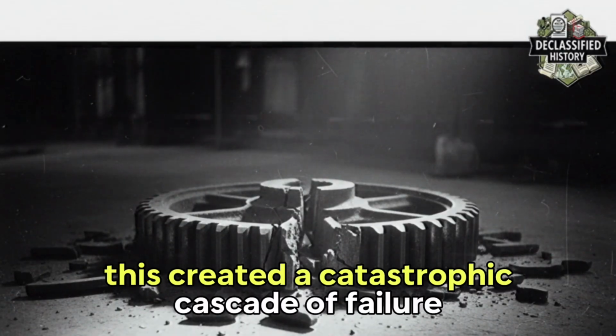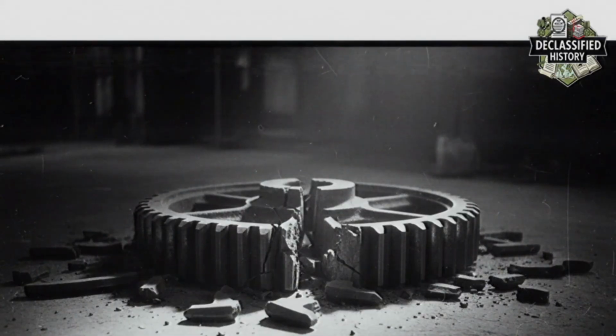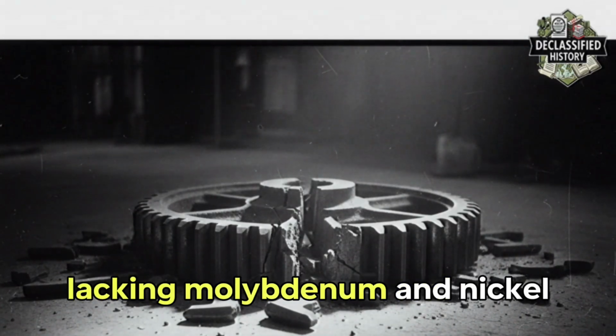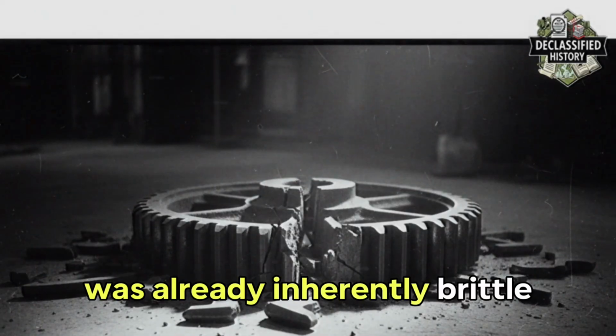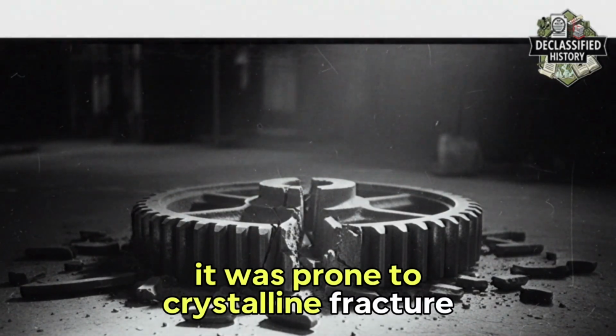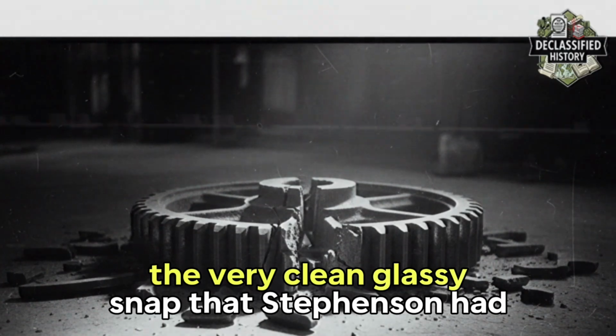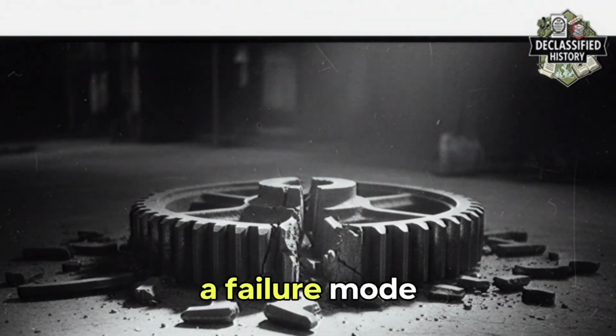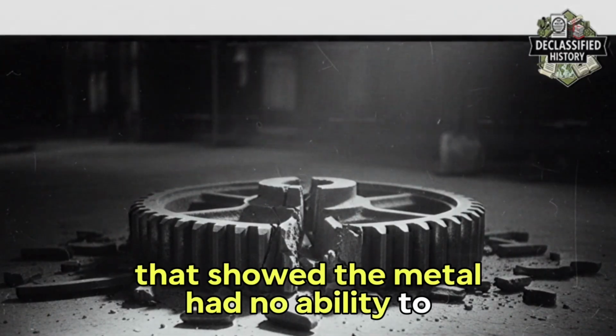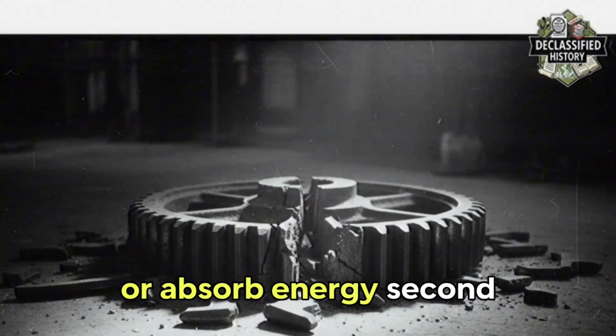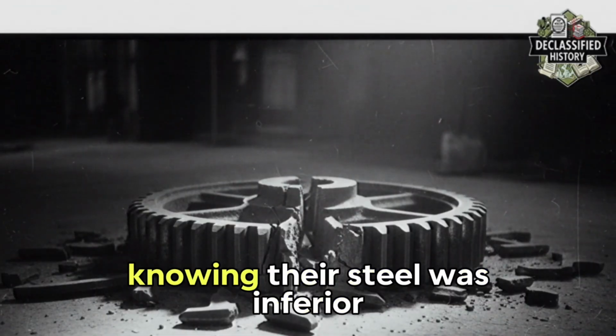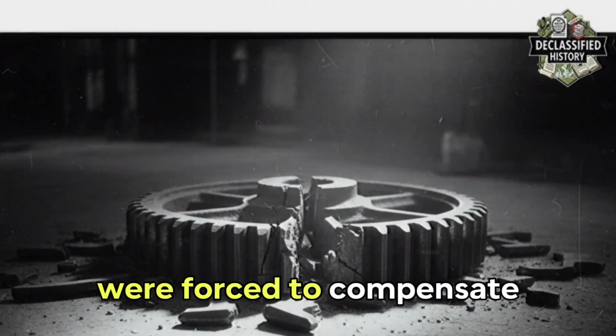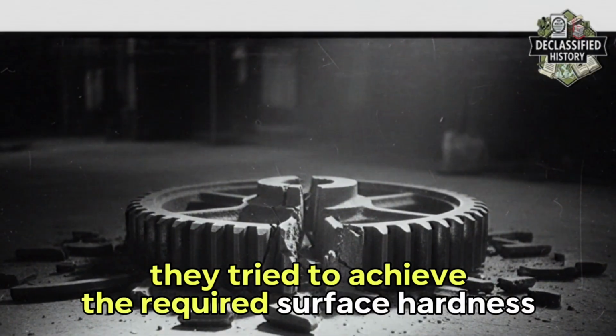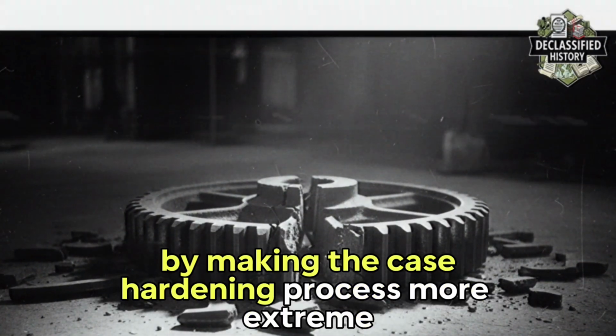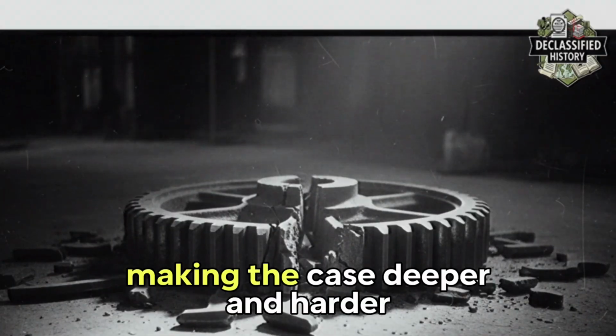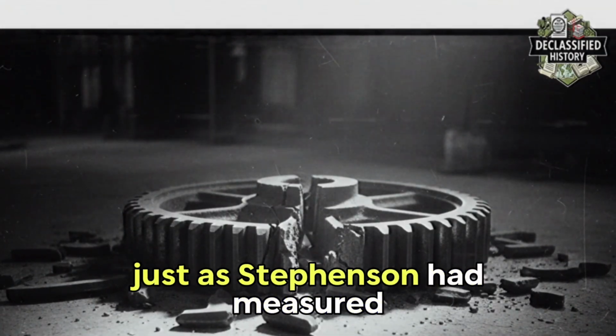This created a catastrophic cascade of failure. First, the base steel, lacking molybdenum and nickel, was already inherently brittle. It was prone to crystalline fracture, the very clean, glassy snap that Stephenson had observed, a failure mode that showed the metal had no ability to deform or absorb energy. Second, the German metallurgists, knowing their steel was inferior, were forced to compensate. They tried to achieve the required surface hardness by making the case hardening process more extreme, making the case deeper and harder, just as Stephenson had measured.